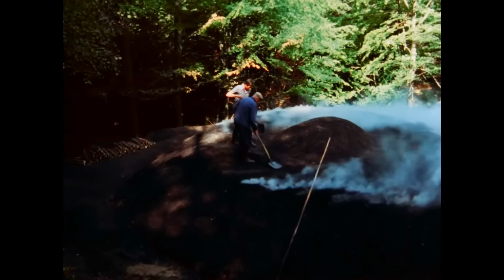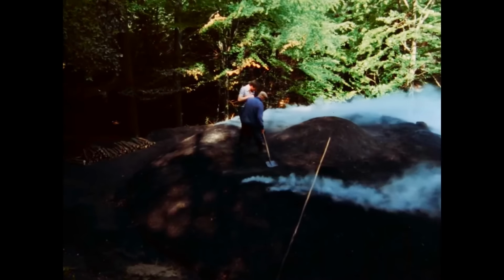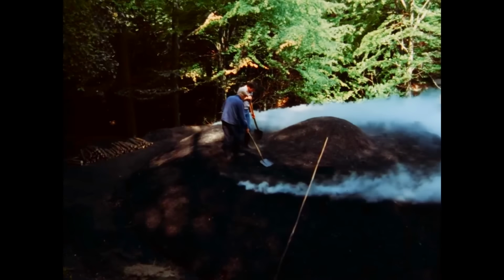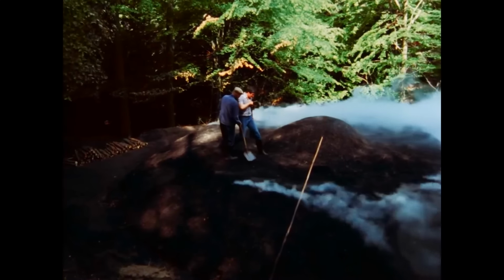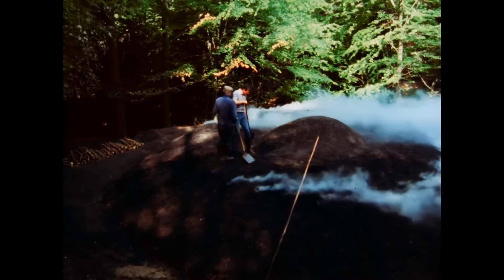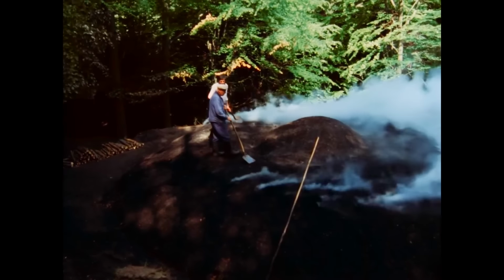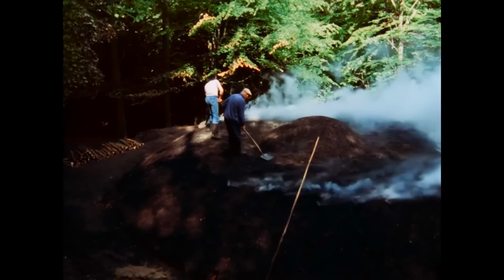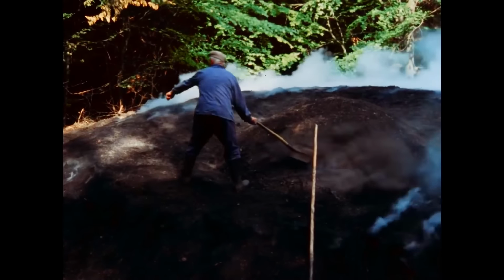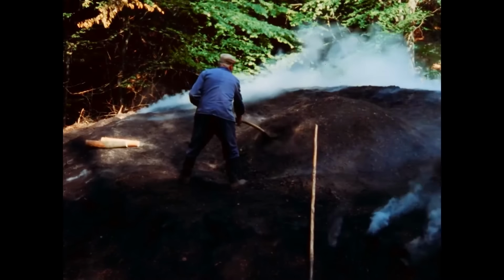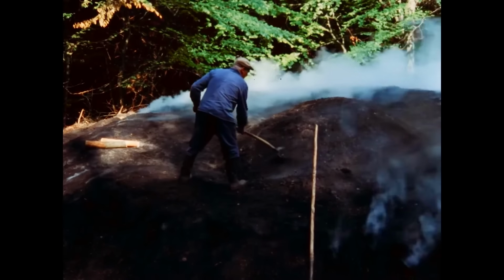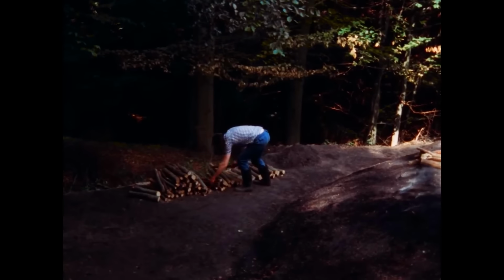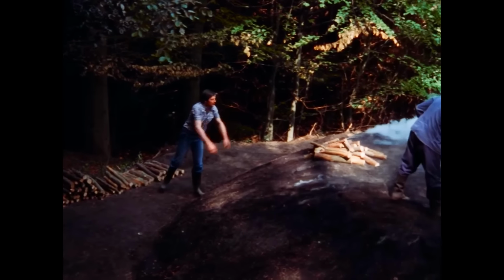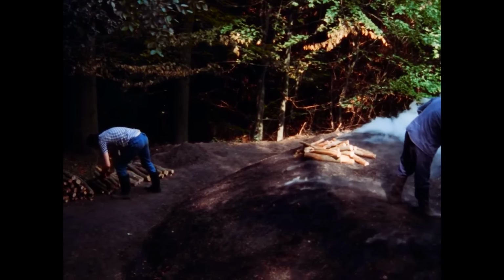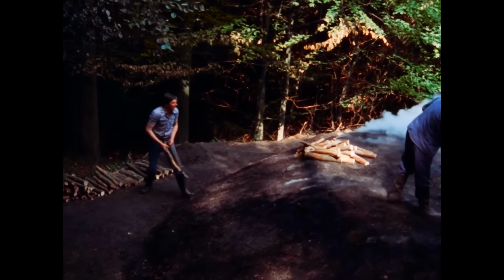Hubert and Wolfgang Stollenwerk spot a cave-in on the kiln's wall. Cave-ins happen when wind pushes unevenly on the mound, or when voids form because finished charcoal wasn't tramped down properly. Either way, the coals get too much oxygen and the wood burns to ash instead of charring. This spot must be opened quickly or the whole kiln could catch fire.